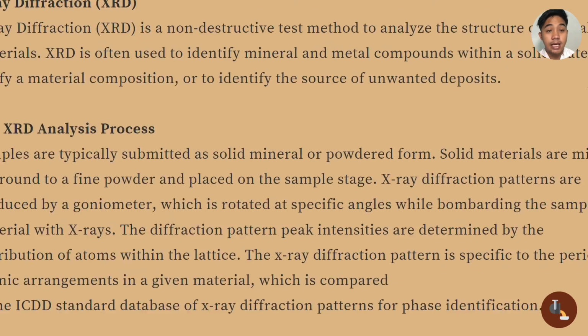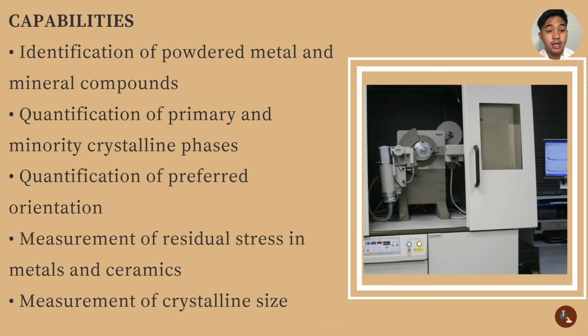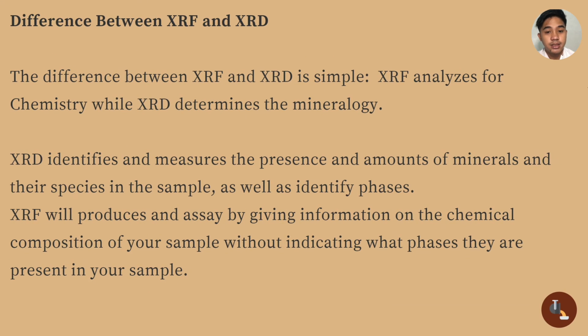Now, these are its capabilities: identification of powder metal and mineral compounds, quantification of primary and minority crystalline phases, quantification of preferred orientation, measurement of residual stress in metals and ceramics, and measurements of crystalline size. Now, the difference between XRF and XRD is that XRF analyzes for chemistry while XRD determines the mineralogy. XRD identifies and measures the amounts of minerals and their species in the sample, while XRF produces an assay by giving information on the chemical composition of your sample without indicating what phases are present in your sample.